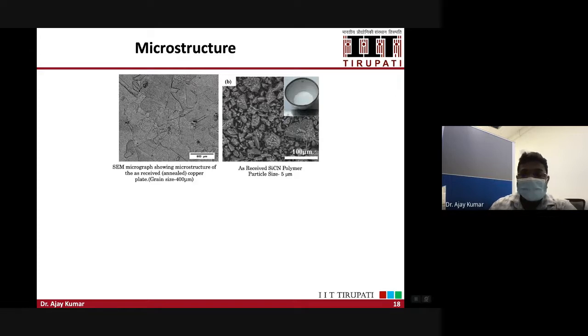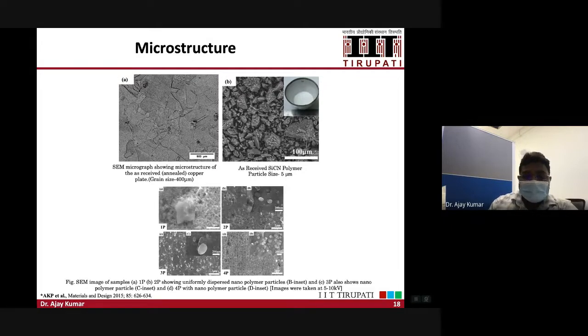Now let me take you towards the microstructure. When you see the annealed copper microstructure, you can see the grain size of this copper is around 400 micron. And the silicon carbonitride, the polymer cross-linked powder, we got around 5 micron. What we did in the first step, we mixed this cross-linked polymer into the copper matrix and did the 4 multi-pass. So you can see here, from the first pass to the fourth pass, the size of these polymer particles is decreasing, and it is going into the nanoscale.